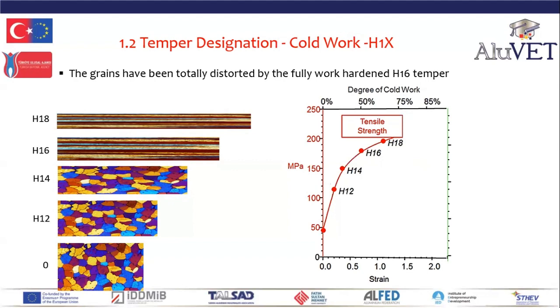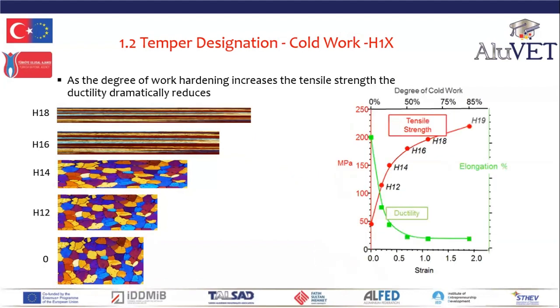So we've gone from annealed to H12 to H14 to H16 to H18 with the corresponding increases, and H18 is the fully work hardened condition. Now, as the degree of work hardening increases, so does the tensile strength. But correspondingly, the ductility reduces dramatically, much faster than the increase in tensile strength.